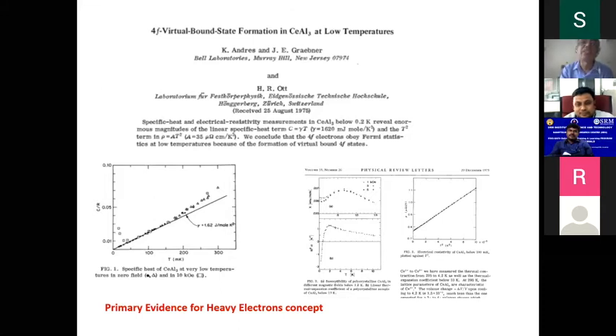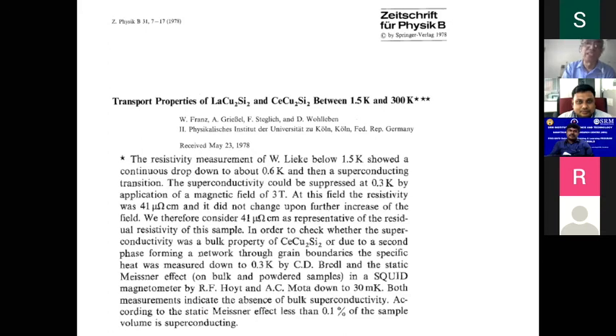Okay, so this is the paper that led to the idea of the heaviness. C is equal to gamma T. Heat capacity is equal to gamma multiplied by T. Gamma is a heat capacity coefficient, which is a measure of density of states at the Fermi level. Therefore, density of states is very large here. Therefore, the system is very heavy. Therefore, the terminology was coined, and people are studying more materials.